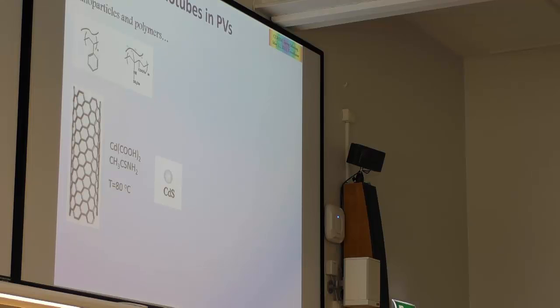So now you have a hydrophobic polystyrene, which normally will be attracted to the aromatic part of the nanotube, and you have a hydrophilic polymer which will be tangling like a brush along these polymers, and now you have a nanotube that is suddenly soluble in water, wrapped around in a polymer. Introduce it very simply, introduce some cadmium acetate and thioacetamide up to the temperature of decomposition of thioacetamide, and now you have cadmium sulfide nanoparticles grafted along the side of the polymer, which due to electrostatic interaction the cadmium cation will be attracted onto the hydrophilic part of the polymer.